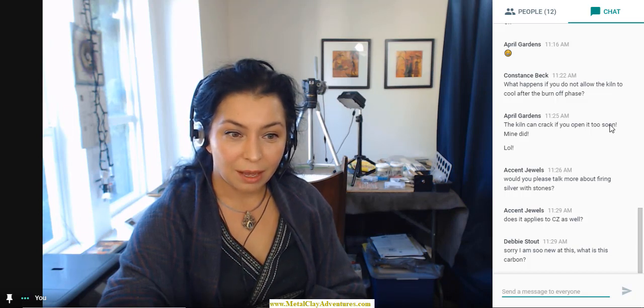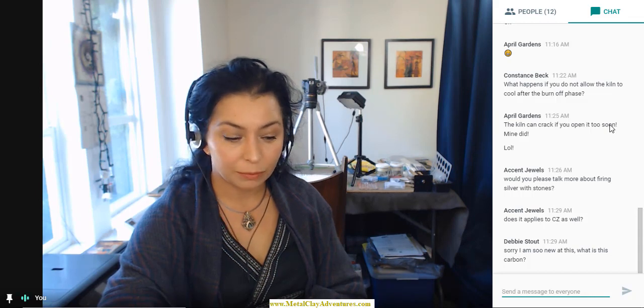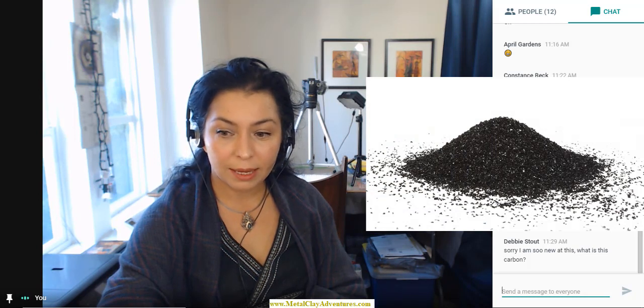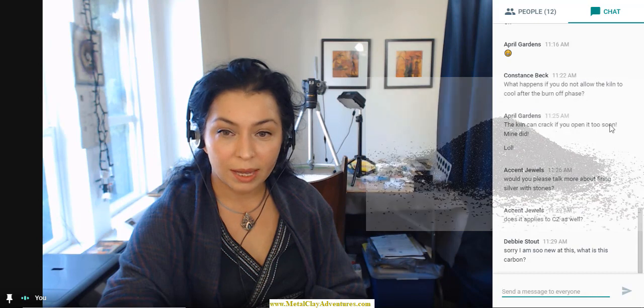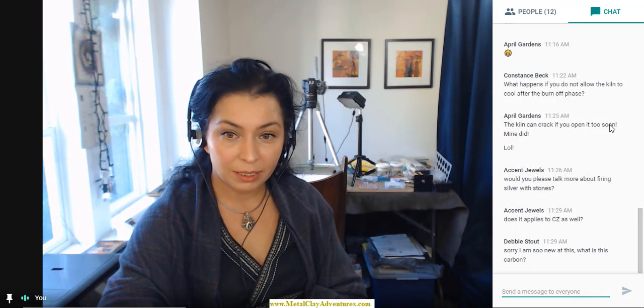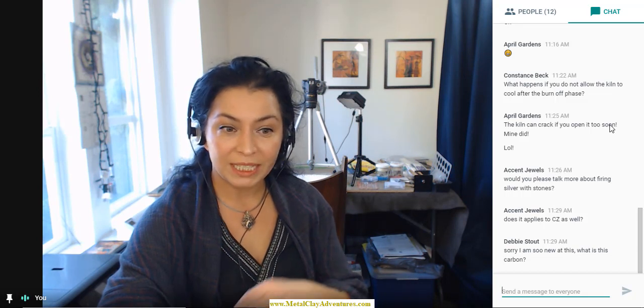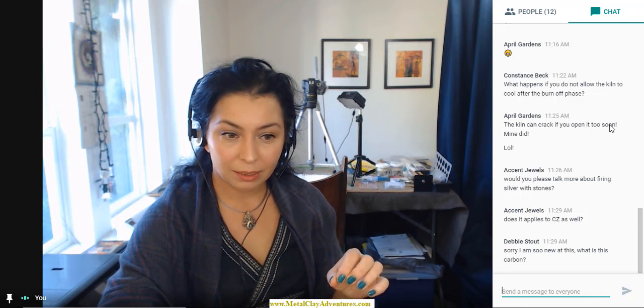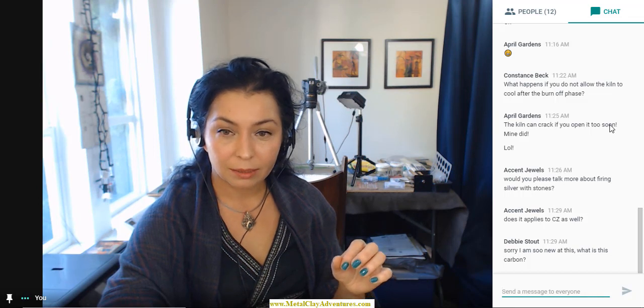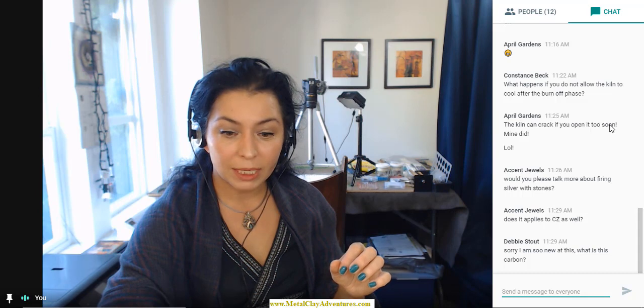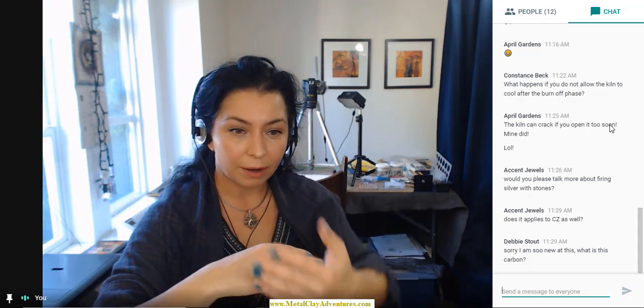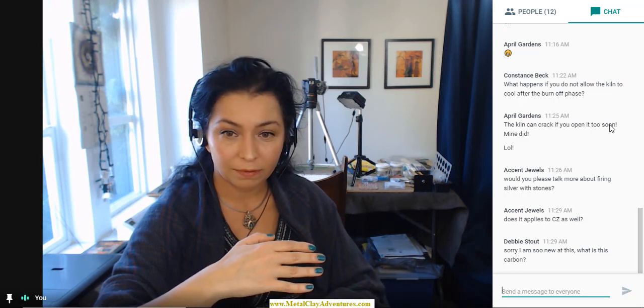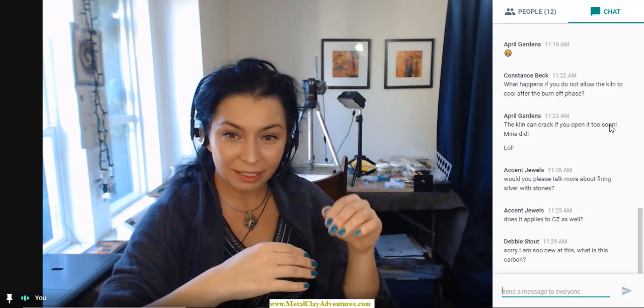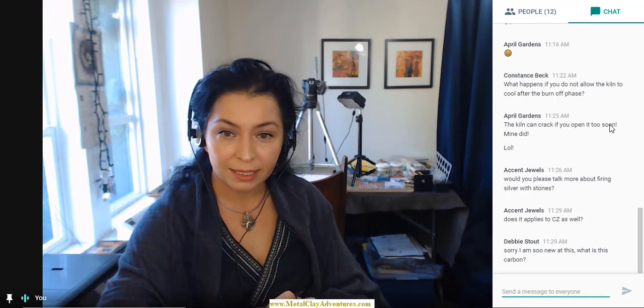Debbie is asking, I'm so new at this, what is this carbon? So, Debbie, we are using coconut activated carbon to fire base metals in order to isolate them from air, because base metals when exposed to high temperature and to oxygen are oxidizing. So when dipping the piece in coconut activated carbon and heating the kiln to more than 1000 degrees Fahrenheit, the carbon is taking fire and is forming like a muffle, a fire around the piece you are firing. And the air cannot penetrate the fire, so the reaction of oxidization doesn't happen.